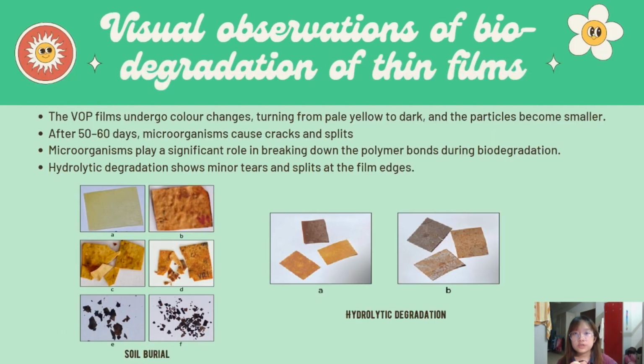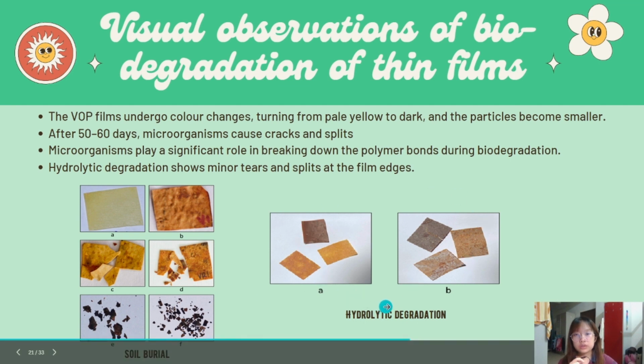The next one is visual observation of biodegradation of thin films. This one is for the soil burial test and this one is for the hydrolytic degradation. From this soil burial test, we found that it undergoes color change, turning from yellow to dark, and the particles become smaller. After 50 to 60 days, the microorganisms cause cracks and splits, because the microorganisms play a significant role in breaking down the polymer bonds during biodegradation. The hydrolytic degradation shows minor tears and splits at the film edge.